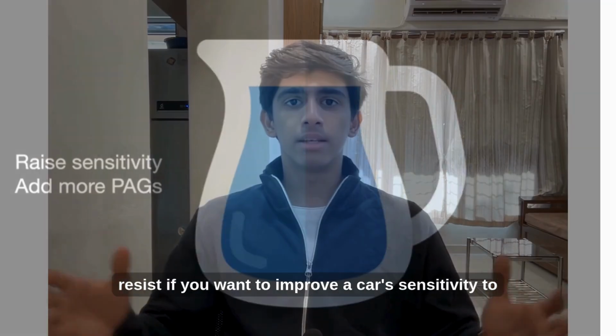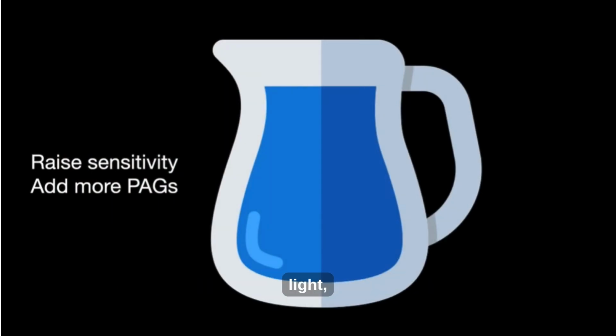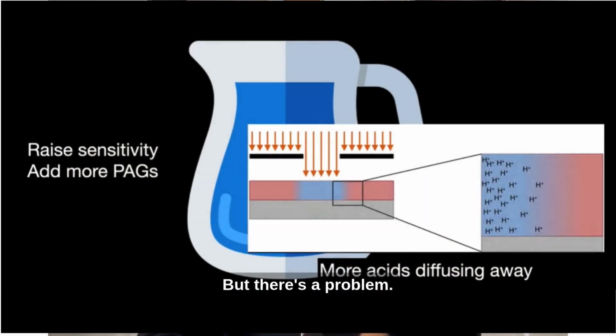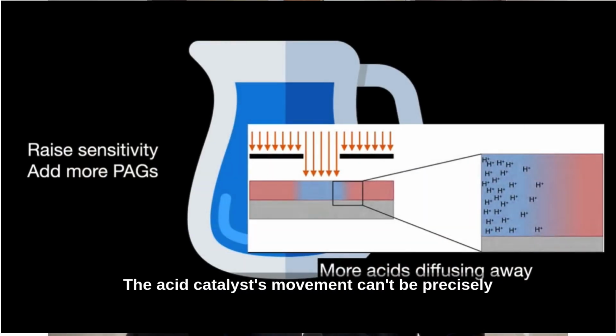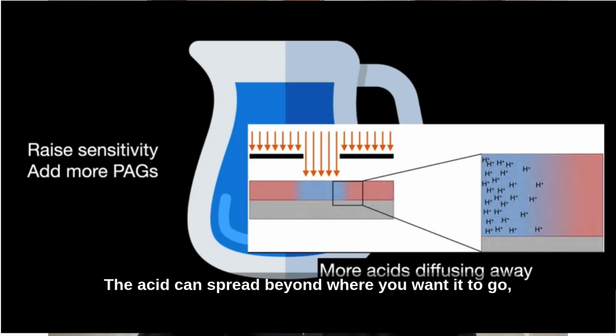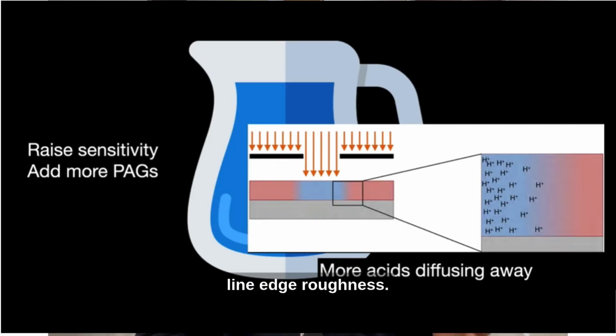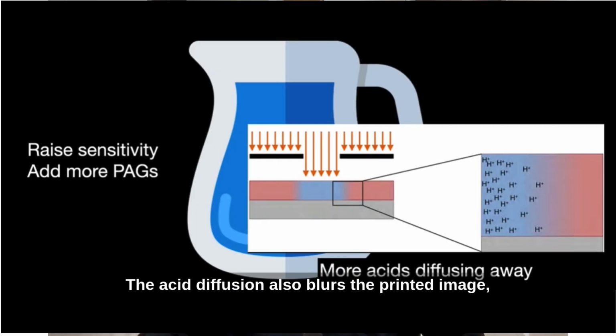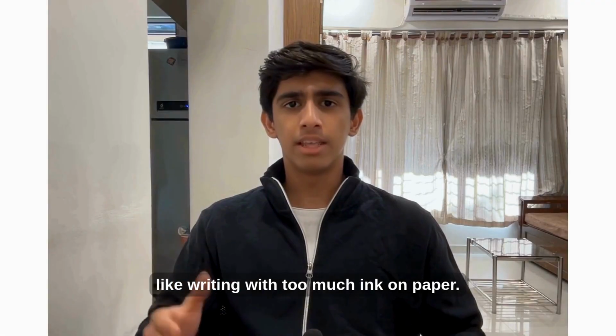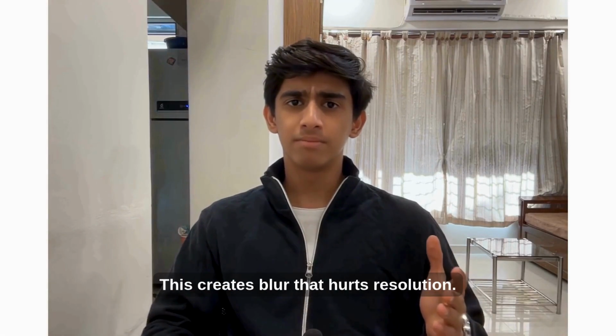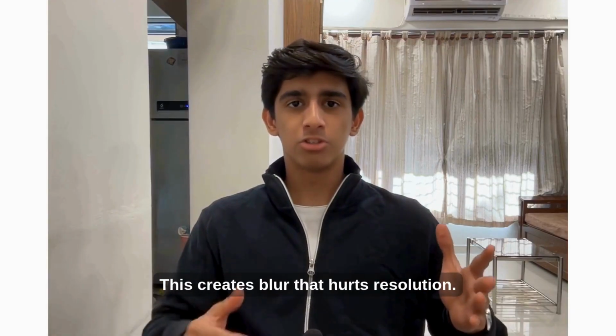For example, if you want to improve a CAR's sensitivity to light, you might intuitively add more photoacid generators to create more acid catalysts. But there's a problem. The acid catalyst's movement can't be precisely controlled. It's stochastic, meaning it's essentially random. The acid can spread beyond where you want it to go, creating unwanted rough edges and hurting line edge roughness. The acid diffusion also blurs the printed image, like writing with too much ink on paper. This creates blur that hurts resolution.